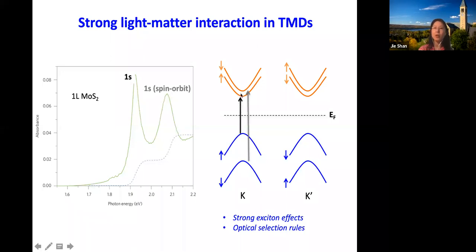The two peaks correspond to transitions between the spin split bands. We'll be mostly focused on the lowest energy one. People often call it the A exciton. I'm showing here the lowest exciton state, and there will also be 2s for this lowest transition, 3s, and so on, when your sample is better. This is from about 10 years ago. Now the sample quality is so good that this peak width is pretty much just limited by the radiative lifetime, on the order of a few meV. Then you can resolve the high energy states much better.